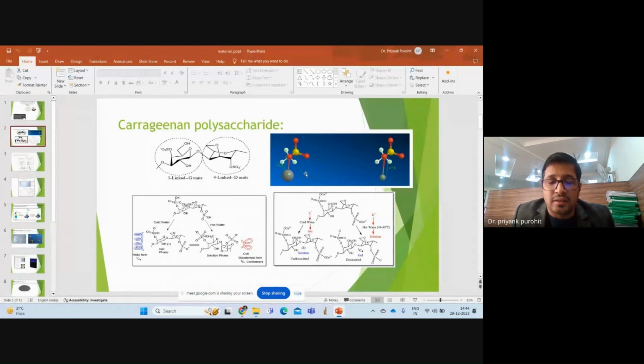Then we again characterized this through the conformational changes. In cold water, it was in solution phase. Why was it so? Because it was not dissociated. Then in hot water, it was in dissociated form and it was in solution phase or reverse phase. So we concluded that the ionic form of this carrageenan is for the gel formation. In this case, if you see, the conformation was 1C4. It means the 1 is on the upper side, 4 on the lower side.